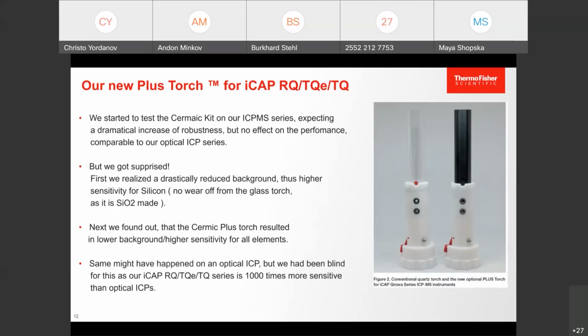But we had a big surprise there, especially for silicon. We realized that our background significantly dropped. This is because quartz glass is mainly made out of silicon. In this ceramic torch, we also have a little bit of silicon, but the content is not so high. So after burning this ceramic torch in, meaning running it for 3-4 hours, we got a good background.